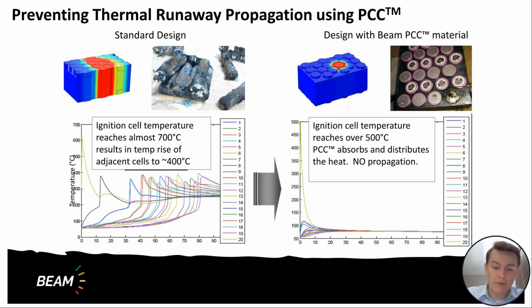Obviously, we take the same pack and replace those PVC holders with our PCC technology, and you can see that the initial failure that we induced with the nail penetration still occurred, but neighboring cell temperatures remain below the critical threshold for these cells, about 150 or 170 degrees. And because of that, there was no propagation that occurred.